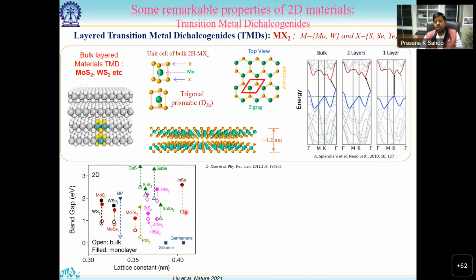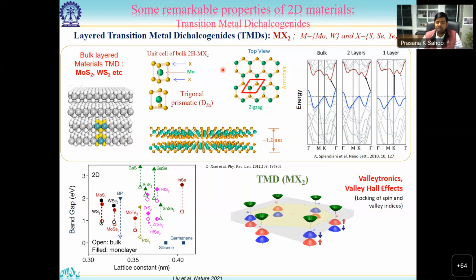It's because of the quantum confinement that the band profile can change. This is interesting because many bulk materials have low quantum yield, but in terms of optoelectronics, if you thin down the material, it becomes brighter in terms of emission. That is interesting, and it is not the case for conventional semiconductors. In addition, in this class of semiconductors the valence band is very unique. There is a splitting of the valence band.